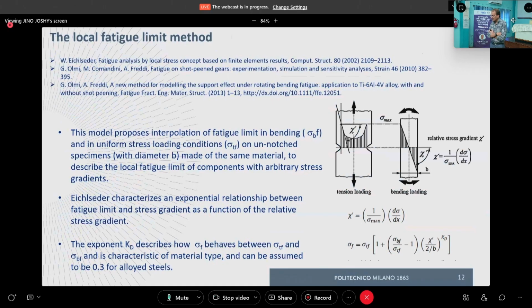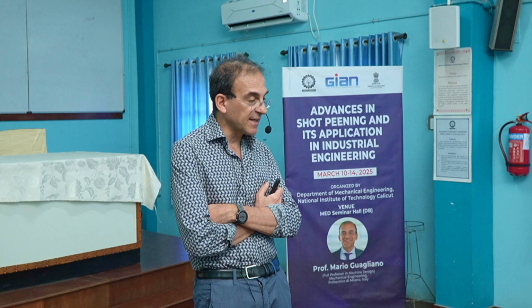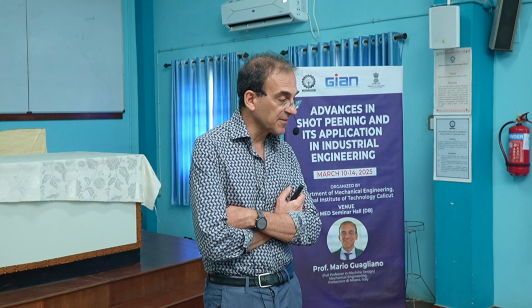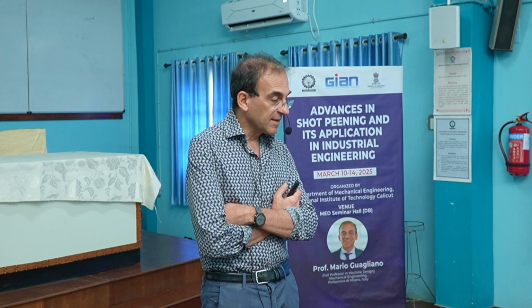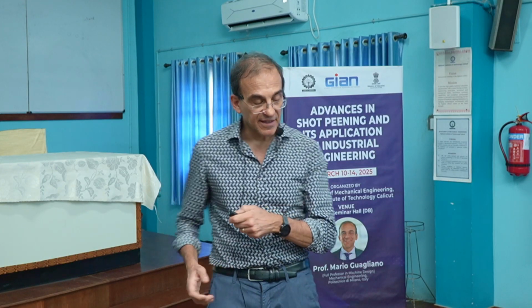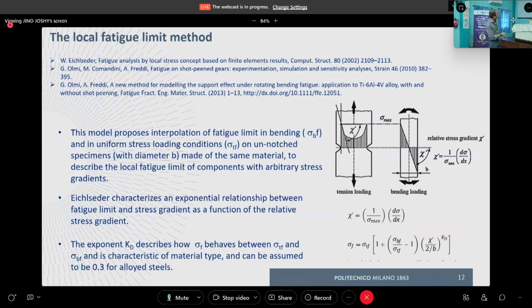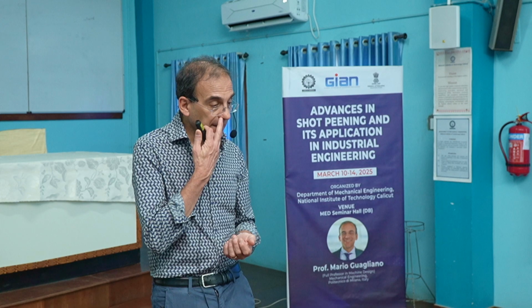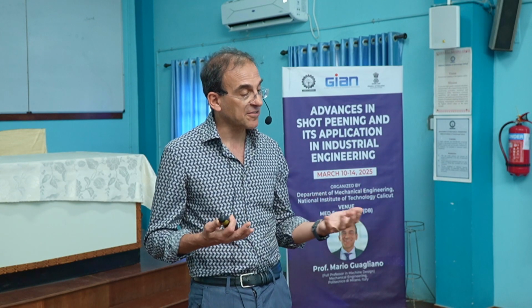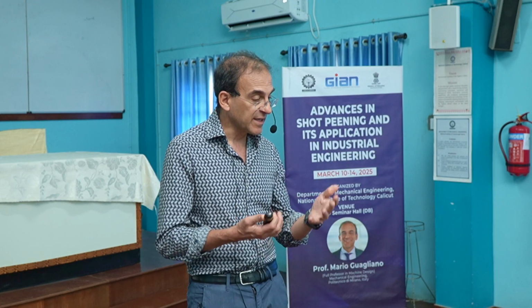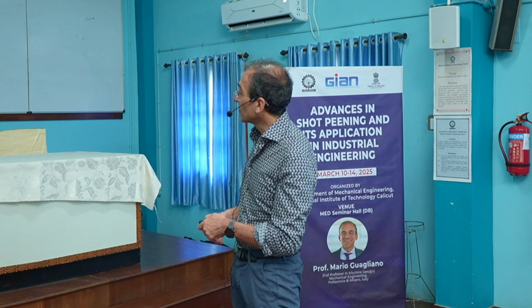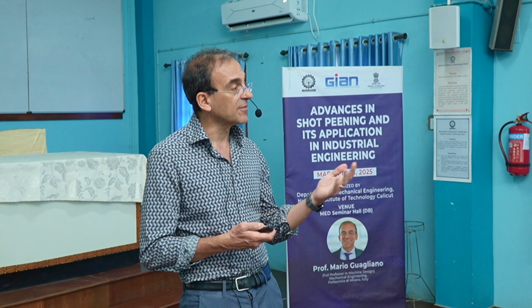Okay. So finally, some comment, the model proposes interpolation of fatigue limit in bending and uniform axial stress condition on an un-notched part to describe the local fatigue limit. And starting from this relative stress gradient, we can apply the same concept to a notched part. We calculate the chi prime, that is the relative stress gradient. We can do that sometimes with analytical formula, much more frequently today by using finite element analysis. And then if we know the basic axial and bending fatigue strength of the material, we can define the terms of this formula and then calculate the fatigue limit of the notched part.